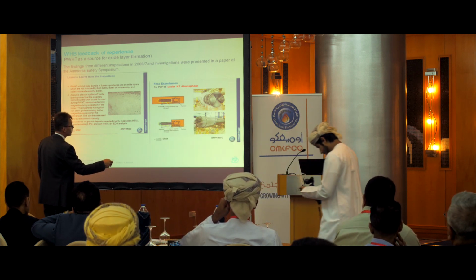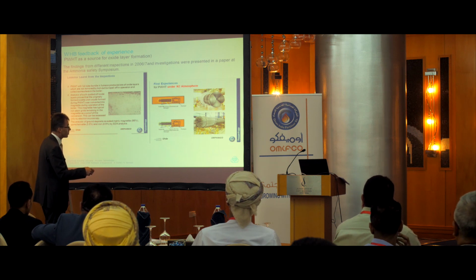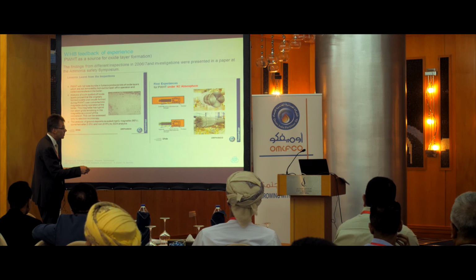If you have a configuration where you do not have a big furnace, some of the manufacturers don't have a big furnace, they have only small furnaces. So interesting for heat treatment is this part, tube sheet shell connection, for example. This is inside the furnace. Outside the furnace was always the tube bundle. In former times, there was no auxiliary shell, we call it, around this tube bundle and also welded here temporarily to the shell, to the tube sheet.